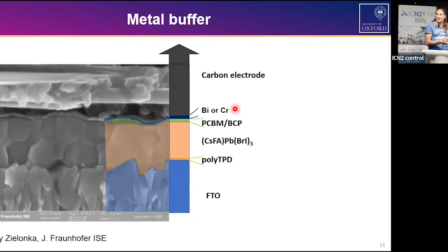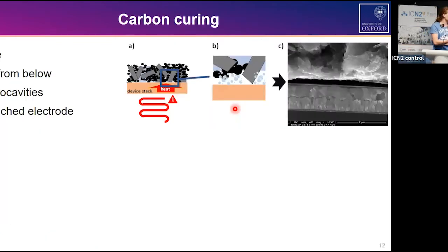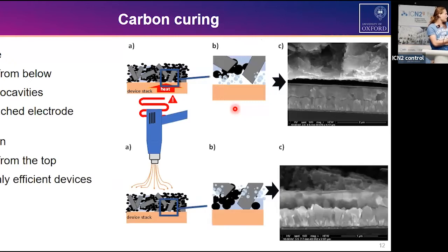And then the next step was looking at what I promised in the beginning, the stability of this layer. And one quick thing we also did for optimization was we changed from a hot plate curing to a heat gun curing, and that solved the initial problems we had. Initially we had our carbon electrode detaching sometimes from the device when not handling it carefully, and an SEM image that looked like microcavities. But the heat gun curing changed that.